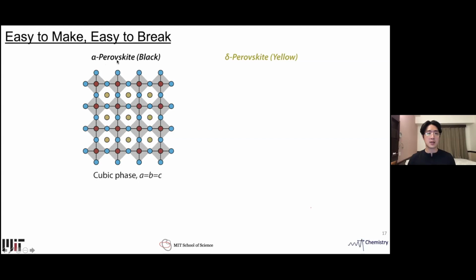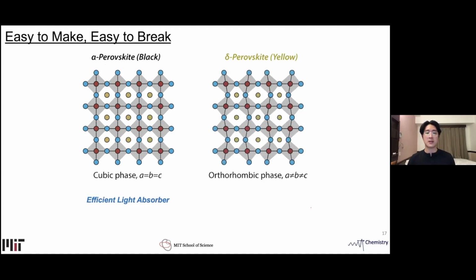The alpha phase is a cubic phase, known to be an efficient light absorber. However, the delta phase, which is an orthorhombic phase, is reported to be a detrimental trap state and also a carrier recombination center.